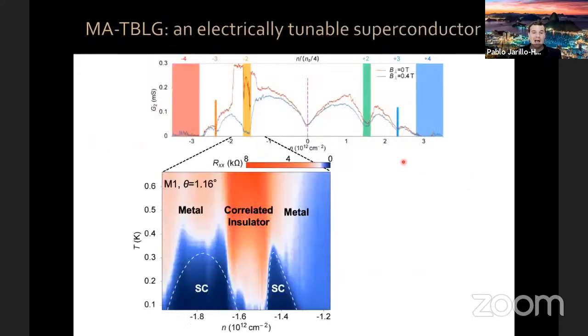Now, as I told you, we can change the charge density because we have a gate and we have this field effect geometry. One of the most interesting things about the system is that you can zoom in around the correlated insulator region, and by changing the gate voltage, you have at this region 2 holes per moiré unit cell, a correlated insulator, and then you add a few holes, you have a superconducting dome. You add a few electrons, you have another superconducting dome.